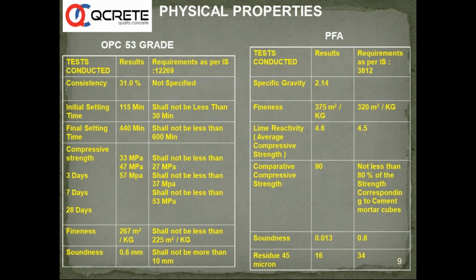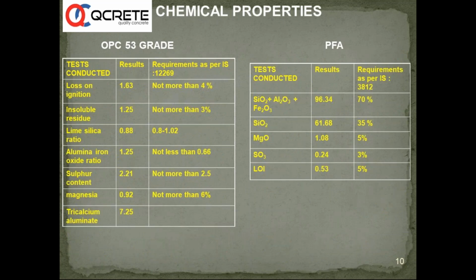Typical physical properties which we need to mention, because most of the users may be checking all these properties, but I just want to talk about the minimum requirements. The requirement as per IS 3812 is 320 square meter per kg. That is the minimum fineness that we need to have. And another most important factor which I need to draw your attention to is residue on 45 microns. As per IS 3812 it should not cross 34%. So any fly ash which comes to a plant having a retention of more than 34% on 45 microns stands to be rejected. We have already talked about the LOI, and we have talked about the SiO2, Al2O3, Fe2O3 requirement.